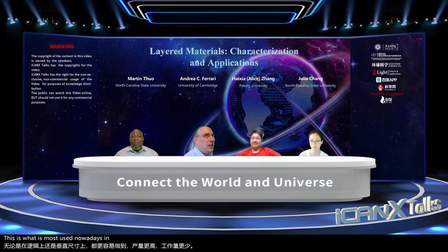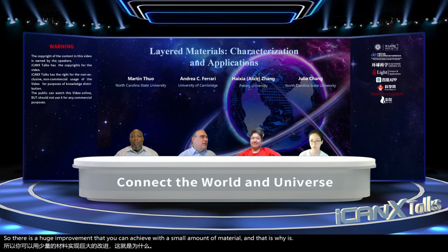In terms of mechanical properties, when you put the graphene ink or the graphene into polymers, with a few percent of graphene, maybe 1%, you can get 10, 20, 30% increase in Young modulus and so on. So there is a huge improvement that you can achieve with a small amount of material. And that is why it is very favorable, especially for aerospace application, because you can basically have the same mechanical properties, but lower weight of the components. And that can also be very useful.